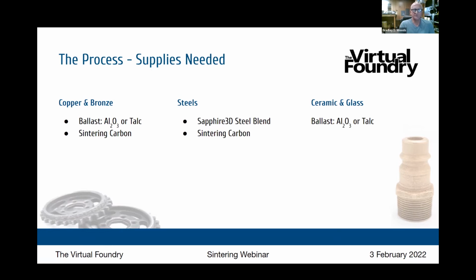Step two is to put it into the talc, and this is just plain old volcanic talc. There's nothing special about it. The reason it works well is it's very powdery and fluffy, so it will yield as your part needs to change size as it shrinks and densifies. It moves out of the way easily, so it provides support at the point where it needs it, but it is able to get out of the way as the part needs to change its shape slightly during the densification part of the sintering process.